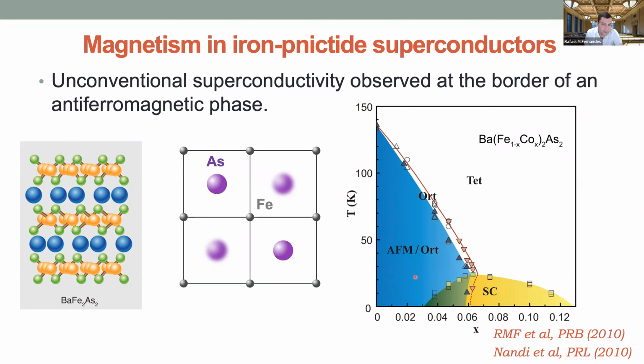This is one of the many phase diagrams that can appear. Often, but not necessarily, you have an antiferromagnetic ordered state at zero doping or zero pressure. Here, for example, you're replacing iron by cobalt, so you're adding an extra electron. You suppress this magnetic transition, and then you get a superconducting dome. This is not very high, but there are other higher transition temperatures.